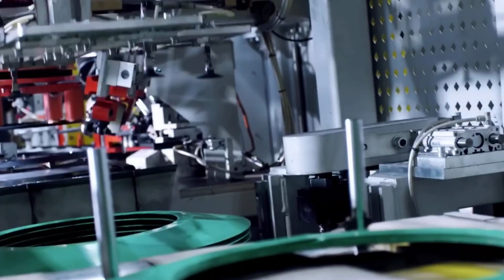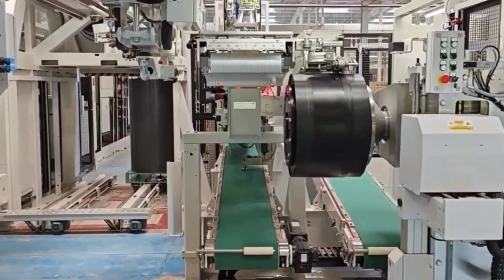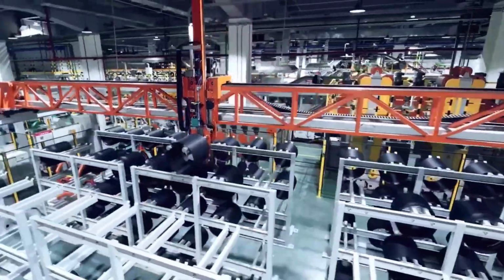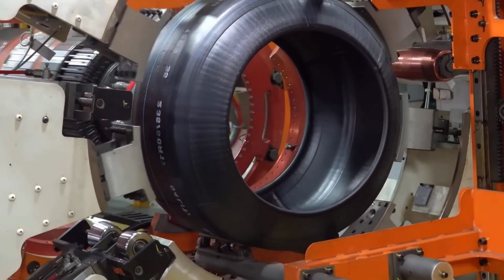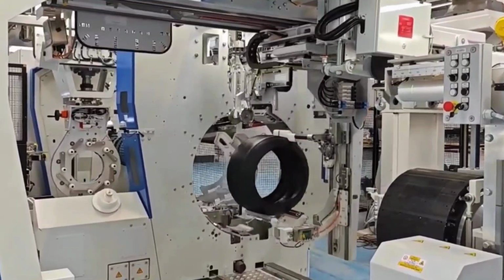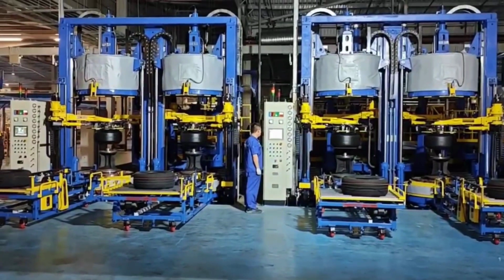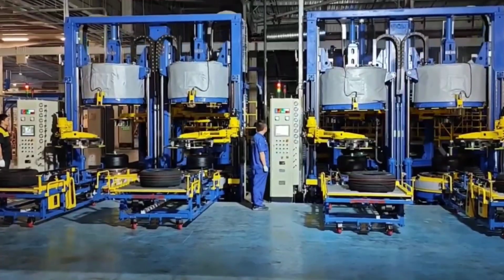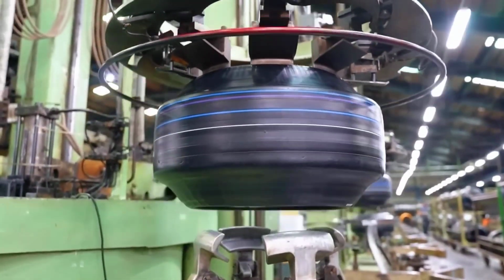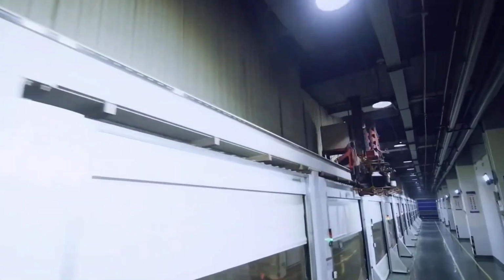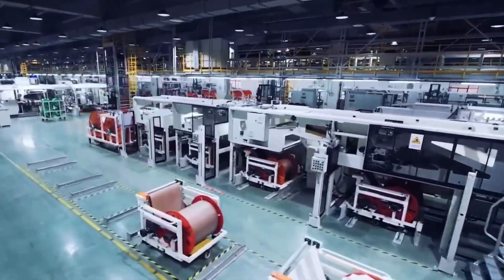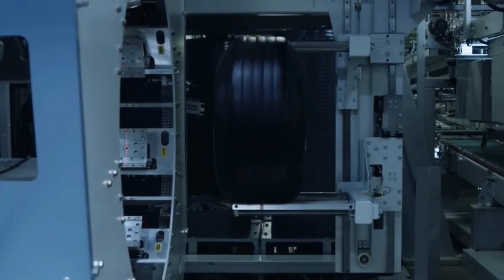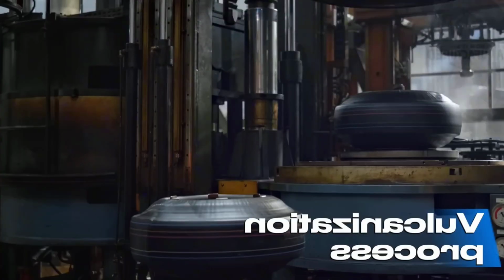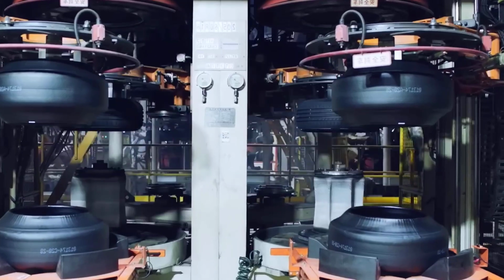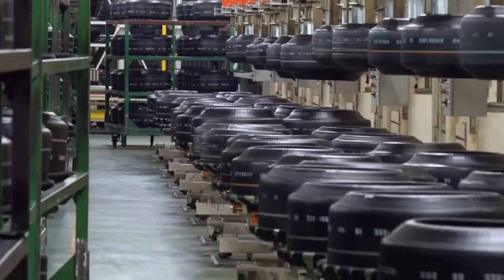As soon as the raw structure is built, the next phase begins: inflating the tire body with compressed air. The internal pressure causes the soft rubber shell to expand and conform precisely to its intended shape. This marks the first transformation, from a collection of separate materials into a unified, cohesive form. Pressure sensors and shape scanners monitor every subtle change. If any deformation is detected, the system halts immediately for correction. In just a few seconds, the basic shape of the tire is complete. A raw but promising structure, ready for the next stage of transformation into a final product built for strength, precision, and endurance.